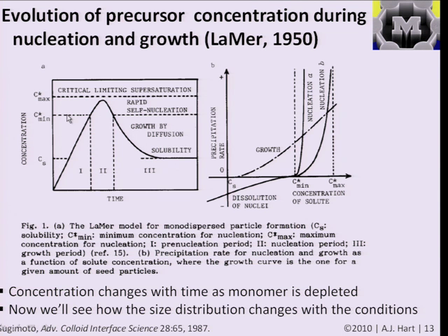And what it's showing here is that if you, say, increase the concentration suddenly, then nucleation will happen, and because nucleation happens, the nuclei consume precursor, then the concentration drops down beneath this threshold, and growth by diffusion, and we'll learn about diffusion now, happens as precursor goes to the particles, and the particles increase in size and end up at a size where they are in equilibrium with the surroundings.